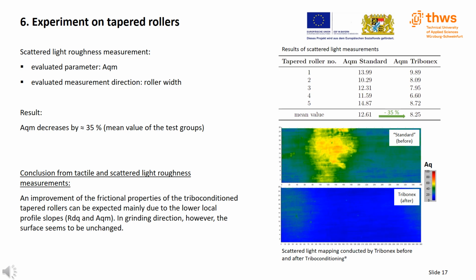Tribonex themselves created a scattered light mapping of the 5 tapered rollers before and after triboconditioning. The mapping of one of the tapered rollers is shown on the bottom right. Here you can see the significant improvement towards lower AQ values at the shell surface. Deviations from the results shown in the table are due to different measurement settings.